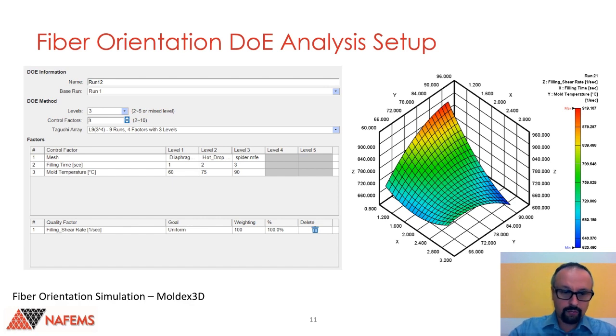In this case, we need to use some kind of substitute for our fiber orientation, because right now it's impossible to directly define fiber orientation as a quality factor for the DOE analysis. So we used shear rate in this case, which in my opinion is directly coupled with the fiber orientation, and it can be used in such a manner. And as a result of this optimization, of the DOE, we have the whole response surface, on which we can see how specific parameters affect our quality factor, our shear rate. Right now we are looking for the minimal value of the standard deviation of the shear rate in the part. So we are looking for the bluest points on our surface here.